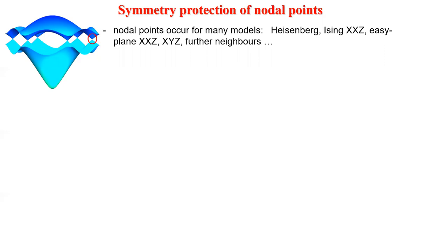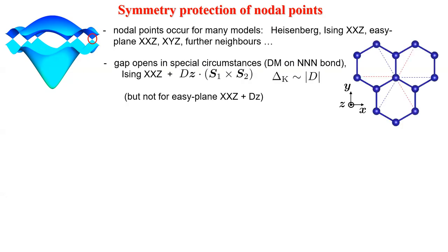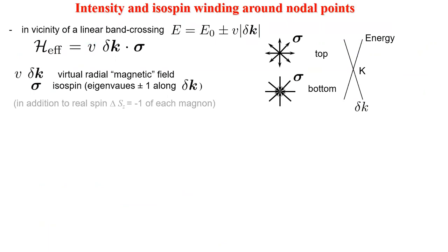So if the size that you integrate is wide, and also having finite crystal mosaic, everything is washed out. So in the most recent measurements on chromium bromide, there's no gap.